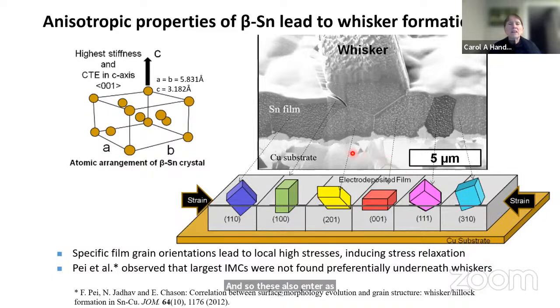So you might be thinking, oh, these intermetallics, if they're causing this, it's just from room temperature growth. If these intermetallics grow and they're wedging up in between the grain boundaries, or partially wetting the grain boundaries, maybe that's where the whiskers form, near where these happen. Pei et al. found that was not the case, that it imparts a more generalized compressive stress to the film, and so they form in places away from where the intermetallics are forming.